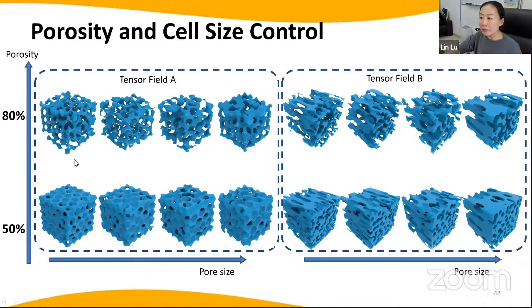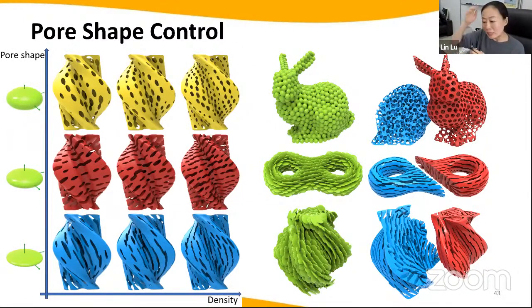So we can get the results, and we can control the porosity here. For example, the upper row is the 80% porosity with different tensor fields. And we can also control the pore size. All our motivation is to compute the biomimetic porous structures, that is organic porous structures. I can also use this modeling as the kernel design with some given tensor field. We can achieve various pore shapes, and then we can get different results.